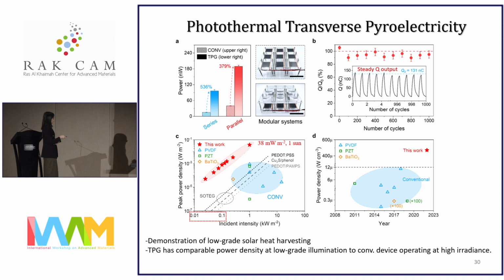So here, I want to quickly show you the state-of-the-art peak power density comparison. It shows that our TPG has a high solar heat harvesting of up to 38 milliwatts per meter square under 1 sun. So the implication is that at very low solar intensity of less than 0.1 kilowatt per meter square, which is an everyday form of illumination for countries outside the equator, or places that are shielded, in shade, or blocked from sunlight, it can now find a useful purpose.